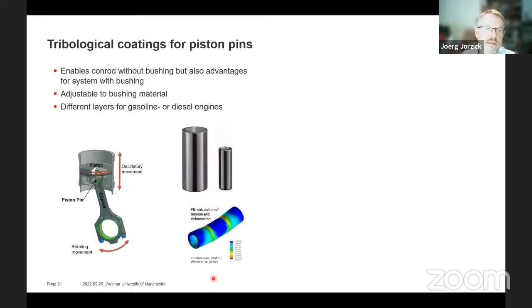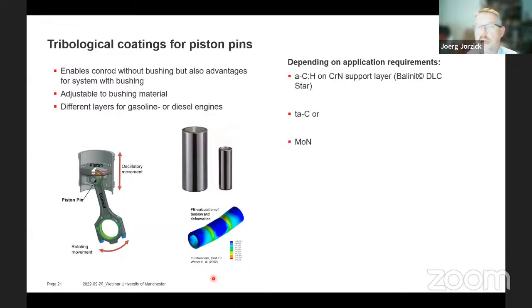So another thing where the automotive industry was requiring modification of the actual coatings, and how we try to support this, is with the piston pin. Here, the standard coating solution is a DLC star. And depending on the actual requirement, we can use this hydrogenated amorphous carbon coating with some kind of support layer. And that is really the standard for the high volume solution that we are offering globally.